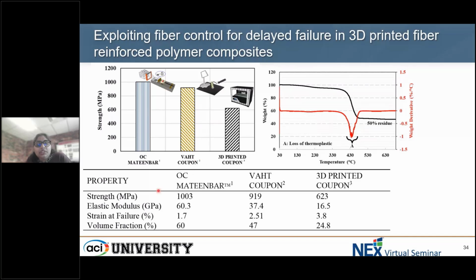If you look at a 3D printed coupon, it's about 600 MPa, compared with 1000 MPa of an OC Mateen bar and 900 MPa of a VAHT coupon. But the amount of flexibility and design variations that can be achieved in a 3D printed coupon is very high when compared to the other two. So that is one of the major advantages of using this 3D printing technology, especially for goals where we want to achieve some high ductility index composites. There is a lot of improvement potential in this technology.